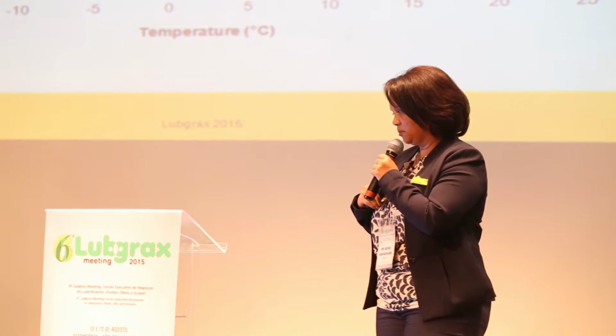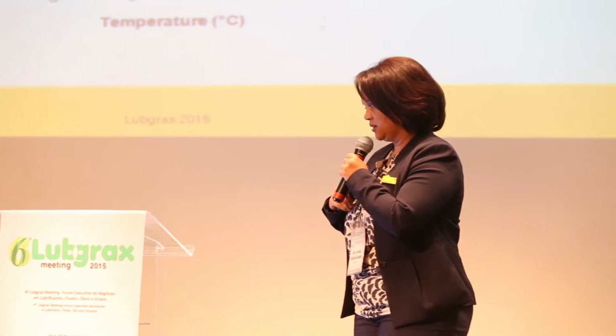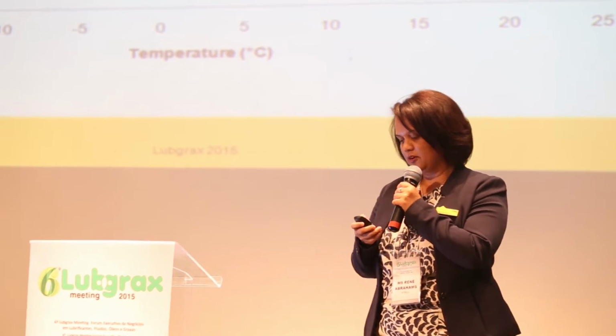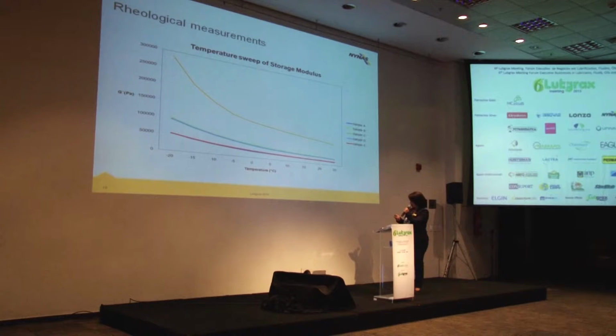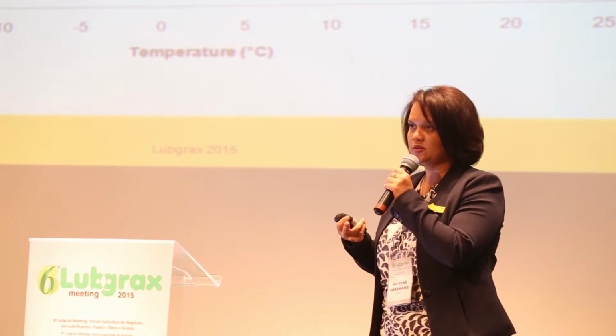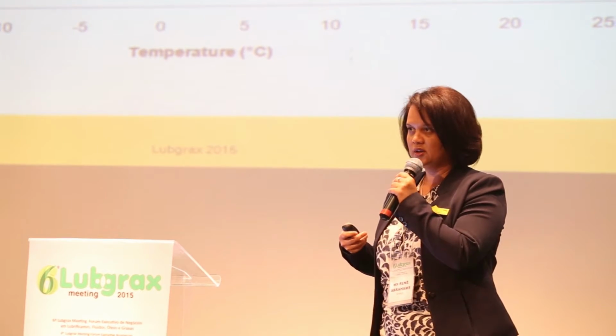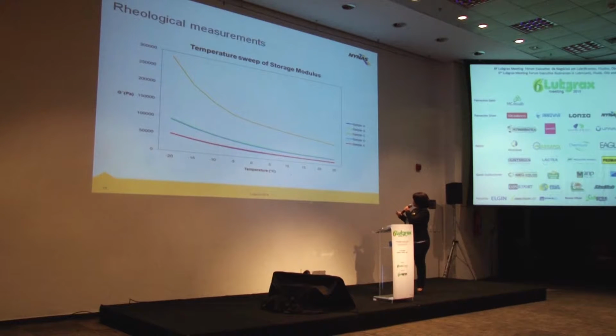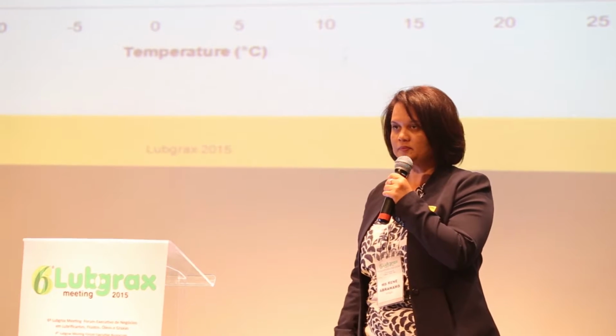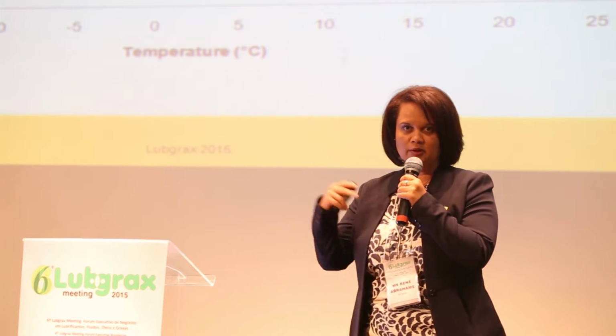Now if you remember earlier on, I think the pour point of the oil in sample C was around minus 15. But of interest here is we see that already at perhaps 0 or even minus 5, the graph moves up almost exponentially. So something happens quite early. Even though you might expect the pour point around here, we see that the grease or the molecules start crystallizing quite early on in the process. Then, just to make note of the starting point here, sample C has a much higher soap content in the formulation compared to the others, and that's why you have a higher starting point.